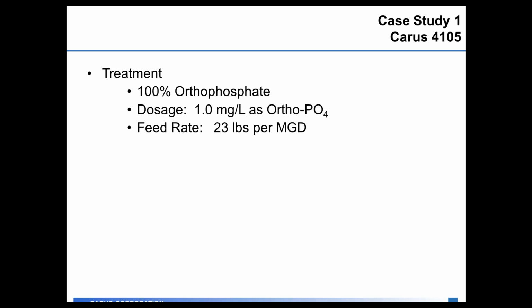So what they chose for their treatment was they were going to go to 100% orthophosphate product, and they chose a dosage starting at 1 milligram per liter as orthophosphate in the distribution system. The feed rate for that product was 23 pounds of product per million gallons treated.